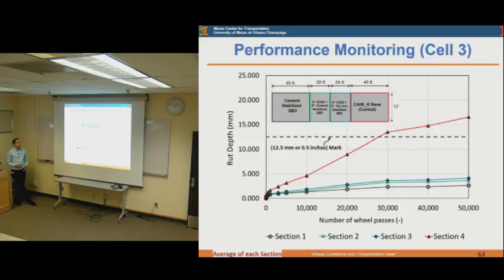Now moving to the performance monitoring of cell 3, in a similar manner. I'm only showing here the results of 50,000 passes, and we have completed up to 100,000 passes, but we didn't complete the experiment yet. We're hoping that we can complete it sometime soon. So the 3 test sections that had the Quarry byproduct cement stabilized, as well as the inverted test sections, had relatively low rutting accumulation up to the 50,000 passes, and that was less than 5 millimeter after 50,000 passes. While the control section actually had a very high or steep increase in rutting over time, and we were also seeing some cracks on the sides of the control section.